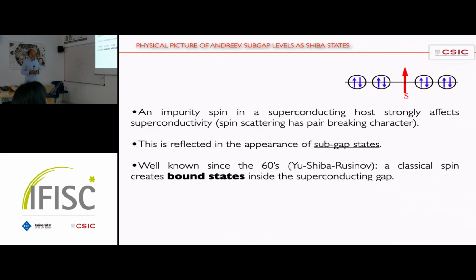Already at the classical level, this problem was well understood in the 60s. The name comes from the three authors who studied this problem, Yu, Shiba, and Rusinov, who demonstrated that even a classical spin coupled to some BCS bath, a BCS superconductor, has strong pair-breaking character. It means that if I put a spin inside a superconductor, this spin couples to the electrons forming the Cooper pairs, and eventually you can break Cooper pairs because of this spin exchange with the impurity. Okay, you can break Cooper pairs.